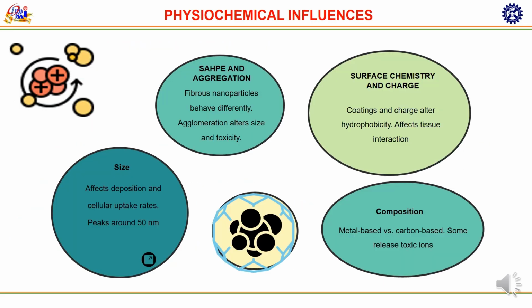Their physiochemical properties that influence this are shape and aggregation, surface chemistry and charge, composition and size. As I say, particle size and surface area play major roles. Smaller nanoparticles have a higher surface-to-volume ratio, which increases reactivity and potential interaction with cells and biomolecules. Shape and morphology influence uptake and distribution. For example, rod-shaped or fiber-like particles such as carbon nanotubes can behave differently compared to spherical particles in terms of cellular uptake and clearance. Surface chemistry and coating is very important. Modifications like surface charge, functional groups, and impurities can affect solubility, protein binding, even toxicity.